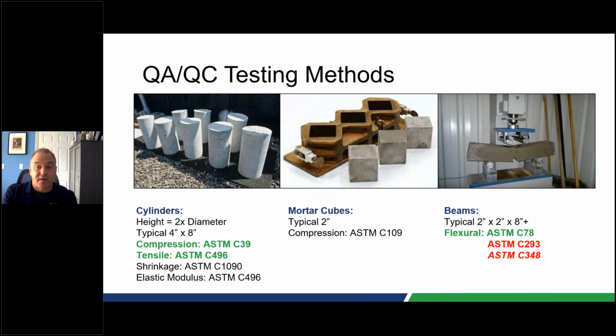We really like to recommend, if someone is measuring compression, that they do cylinders. They can do them through ASTM C39. You can do tensile tests with the same cylinders, another set of them, through C496. You can use mortar cubes. We like to stay away from mortar cubes as best we can. They actually give higher values, which from our view is a less conservative quality control measurement. So I think that you would be interested in pushing those things towards cylinders, which is what we normally recommend.